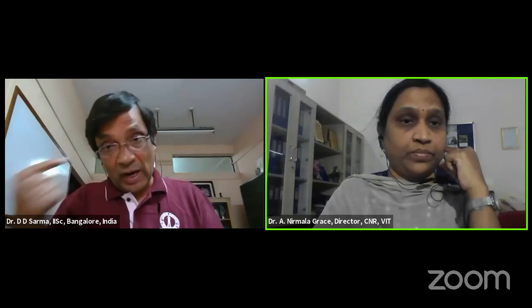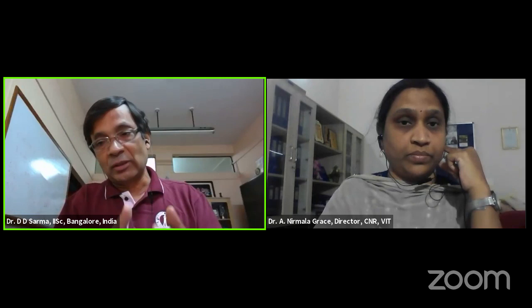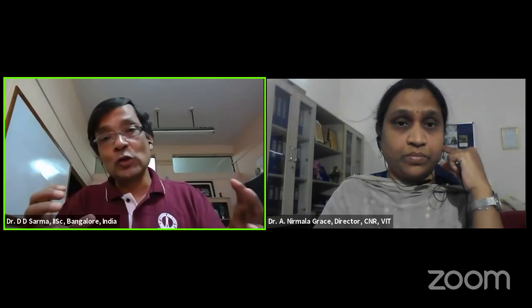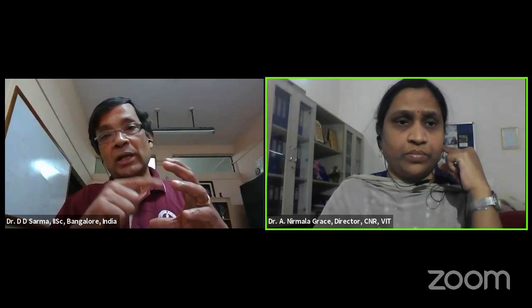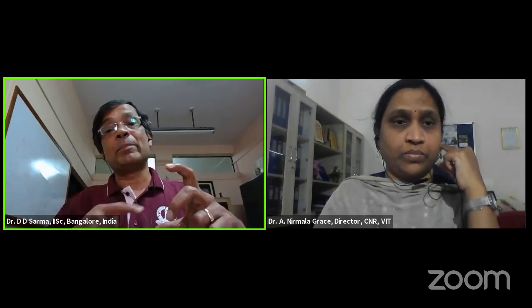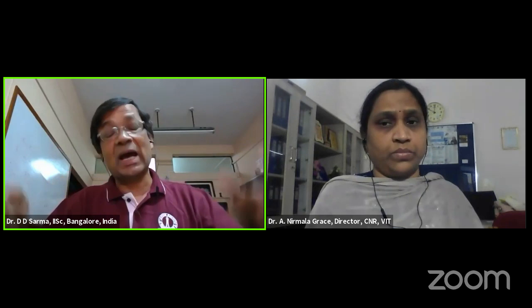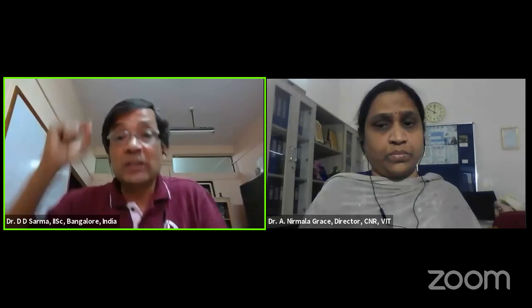And finally, do not forget that the mixed phase is an integral sample. In fact, this is something that we are addressing and we should be submitting the paper very soon. The fact is that there's a lot more twist. It is not a T prime phase that is inside an H phase but not connected to the H phase. The fact that this metastable state grows inside the H phase exerts a lot of strain on both the phases, because there has to be a matching, stitching of the atoms on the periphery, which means that though I have idealized the description in terms of T prime phase, it is not a pure T prime phase. It's a distorted T prime phase and a very complex distortion is taking place and that alters its chemical property, which means that sometimes you might be interested in this mixed phase because it has a unique property which the pure T prime phase will not have.